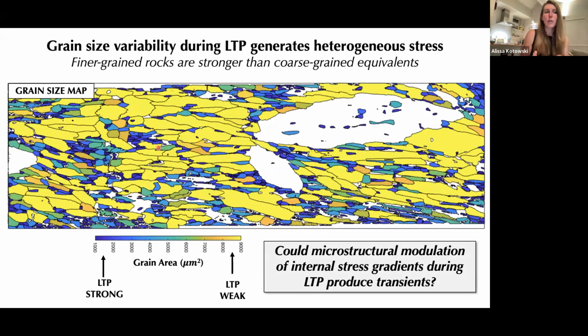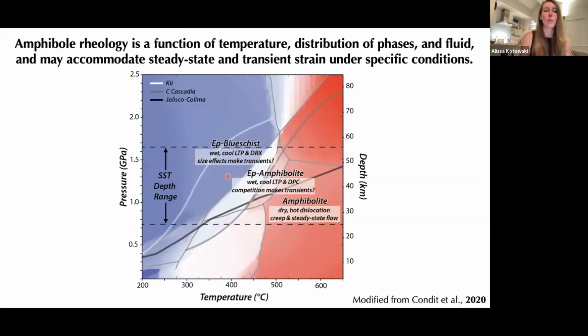Most of us would see this microstructure, and with all the other EBSD data I showed you, we would interpret this as evidence for dislocation creep on its way to a steady state microstructure. But with all the evidence and mechanical data and things that are pointing to low temperature plasticity, I think a different way to view this microstructure is that it might actually have this low temperature plasticity framework. And based on the size effect argument, if this is true, then the grain size here actually has an opposite effect on rock strength than what we typically think of for high temperature creep. So this leads to one last question here, which is, could the microstructural evolution or development and modification of internal stress gradients here during low temperature plasticity actually produce things that look like slip transients?